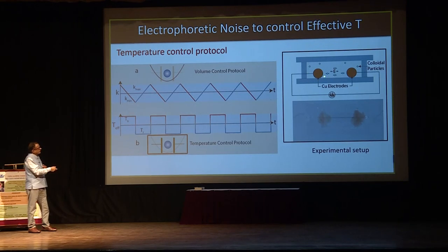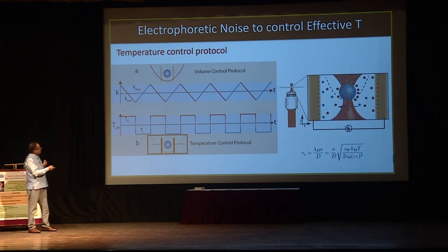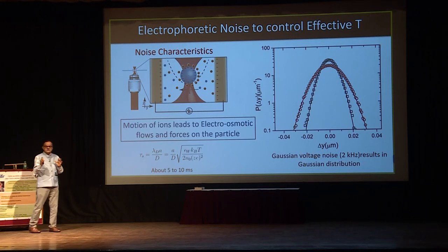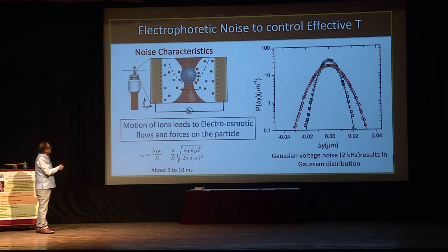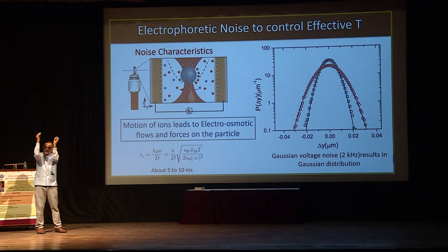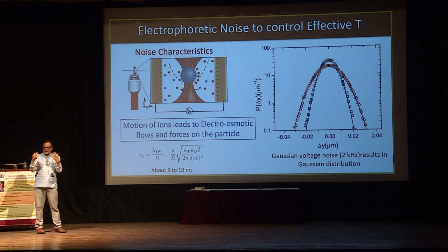You have put two copper electrodes very close, and this is where the colloidal particle is trapped in a tweezer. Do the protocol. I will not go into detail, but the beauty is why it brings the interaction. The reason is when you apply this electrical voltage, you get the ions which surround the colloidal particle. So you have an ion cloud which you have to take care of. That relaxation has a time scale of the order of 5 to 10 milliseconds.